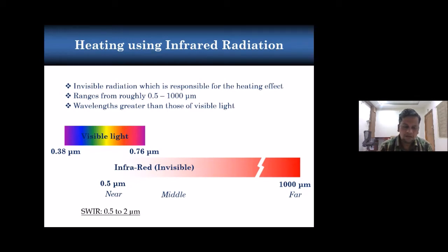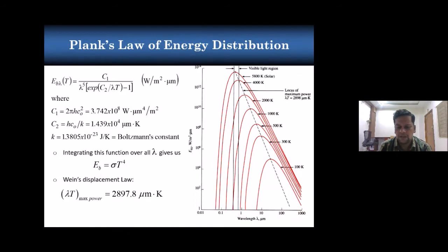Why the short wave infrared is used is because of its energy. We can have a very high amount of energy and temperatures at the lower wavelengths. Now if you see Planck's energy distribution over the wavelength range within the infrared region, you can see this formula, E equals C1 by lambda to the power of 5. This expression shows Planck's infrared energy distribution over the wavelength. If you integrate this energy distribution over the wavelength range, you will get the Stefan-Boltzmann equation, which tells you the total energy content within the wavelength band is directly proportional to the fourth power of temperature.